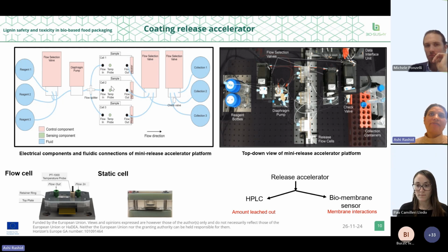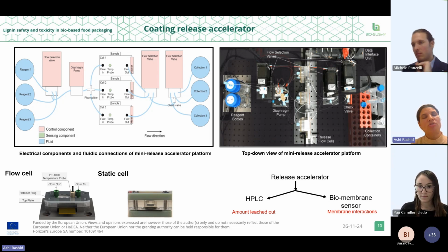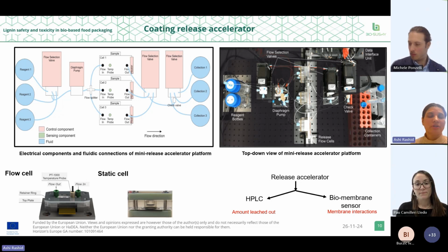These flow cells have a silicon mat heater at the back, which helps increase the temperature of the coating and the reagent in contact with the coating to a certain desired amount. This silicon heater can increase the temperature up to about 300, but we can't go beyond about 80 degrees because of the temperature sensitivity of the different components of this flow cell. But we can raise the temperature up to 80 degrees successfully using these flow cells.